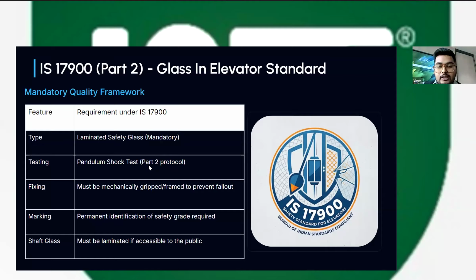Then the pendulum shock test, which I told is the impact test, is a good requirement because the glass should be able to bear a human impact of a weight around 45 to 50 kg. Then we talk about the fixing. The glass should be fixed, mechanically gripped, and framed properly. It shouldn't be like just putting up stickers and placing it roughly. It should be done in a proper way so that the glass can work to its full strength.